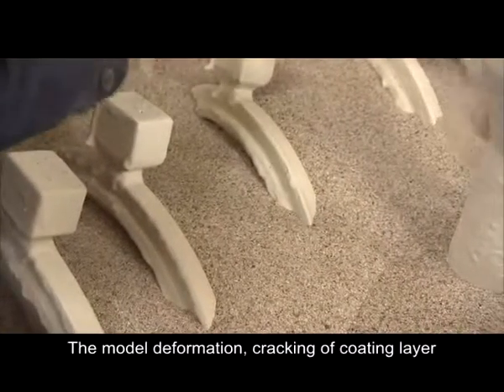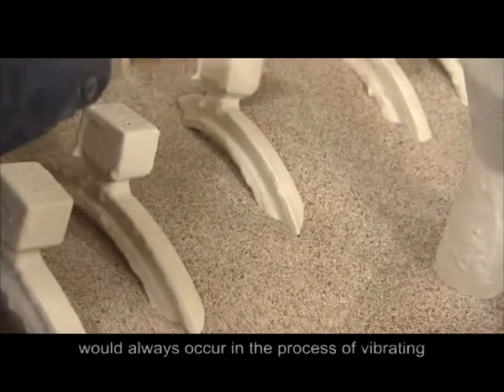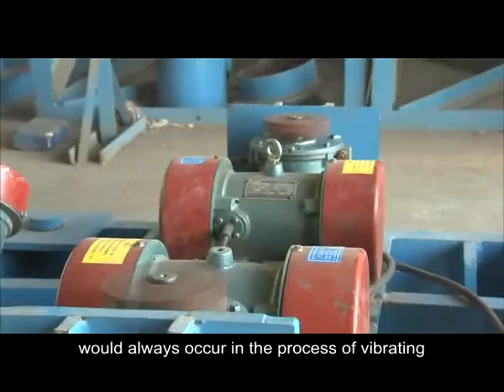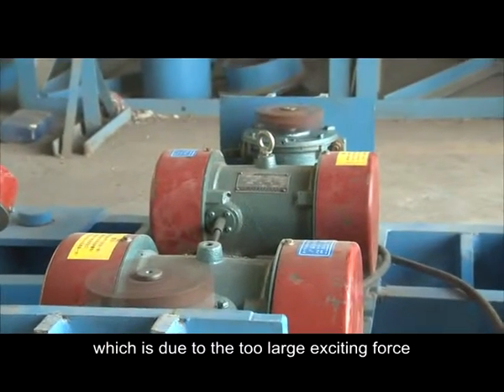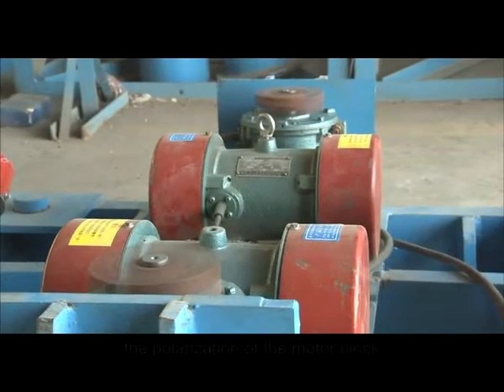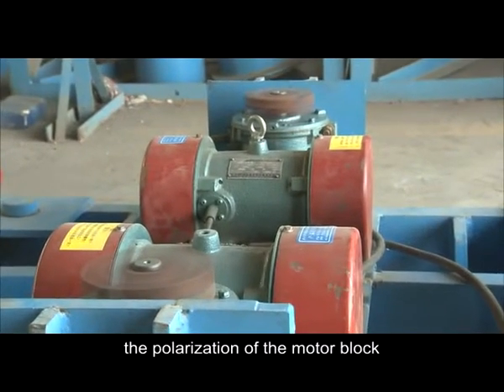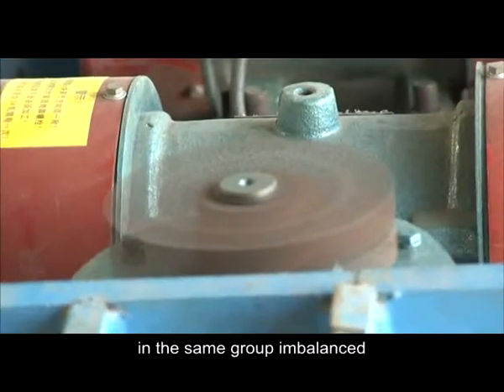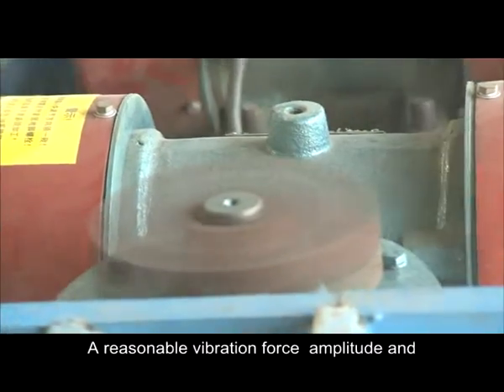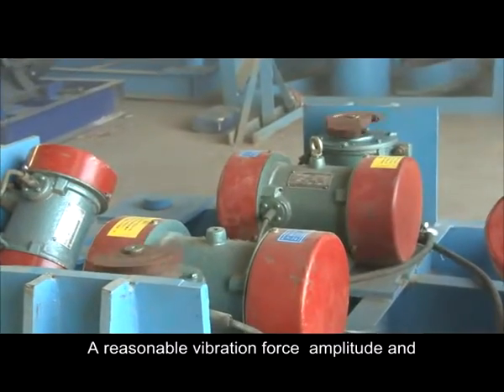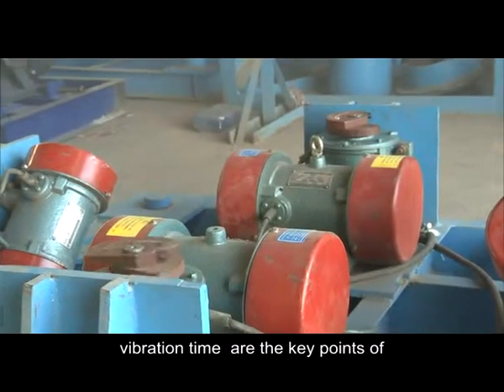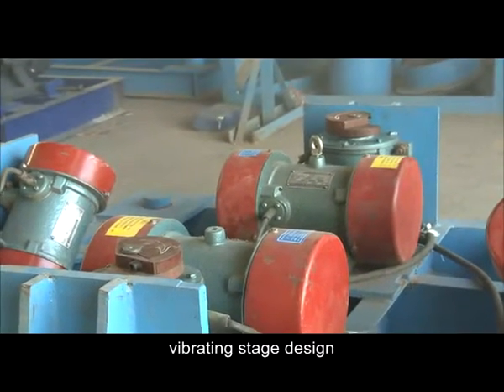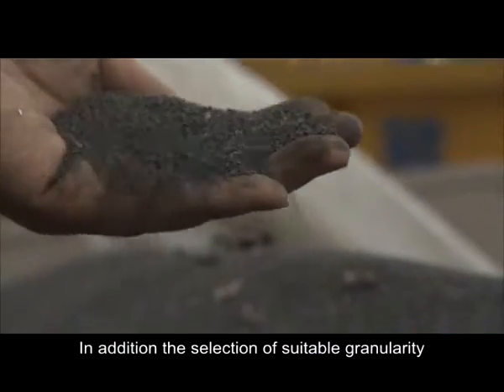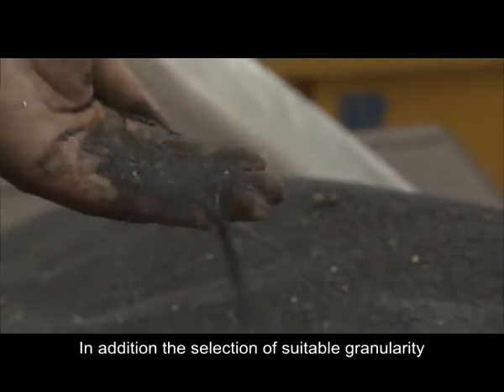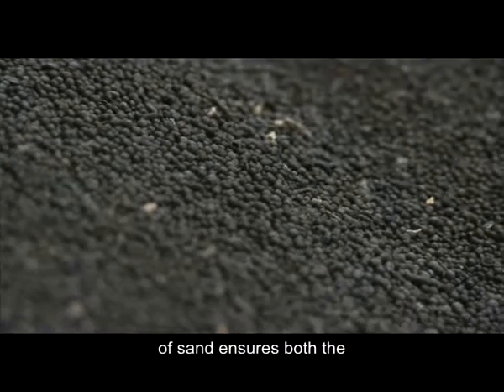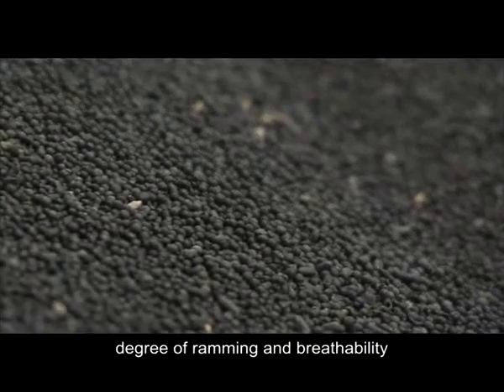The model deformation and cracking of the coating layer would always occur in the process of vibrating, which is due to too large an exciting force, or the polarization of the motor blocks in the same group being imbalanced. A reasonable vibration force, amplitude and vibration time are the key points of vibrating state design. In addition, the selection of suitable granularity of sand ensures both the degree of ramming and breathability.